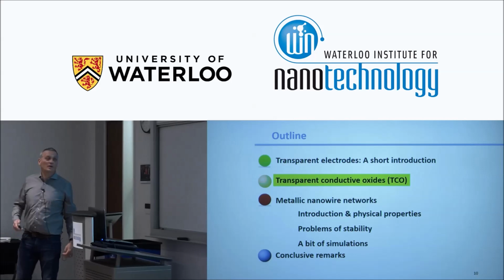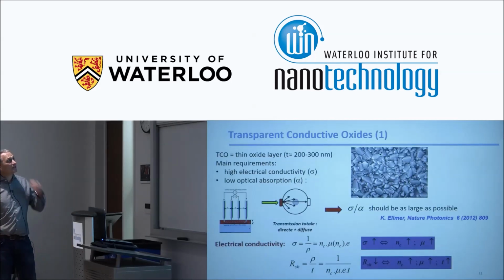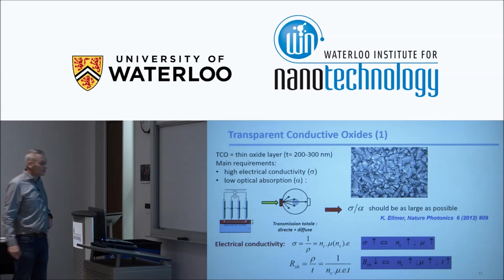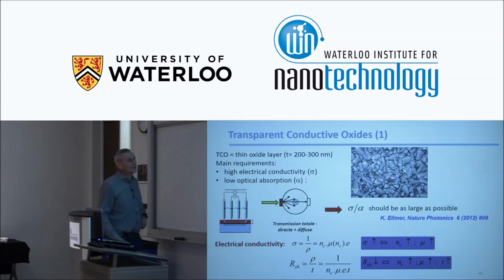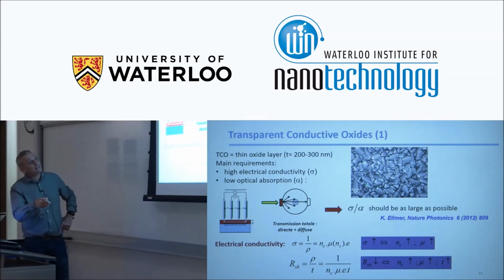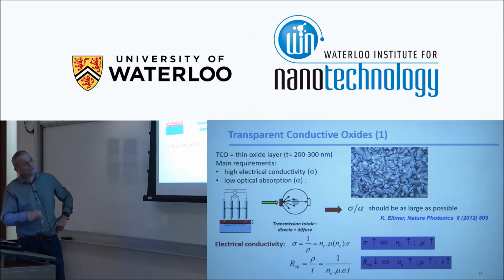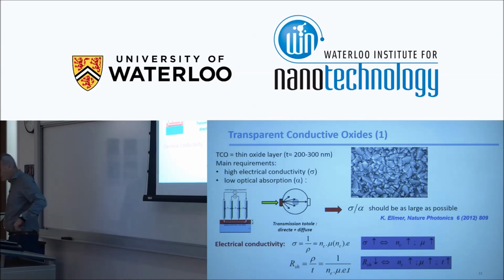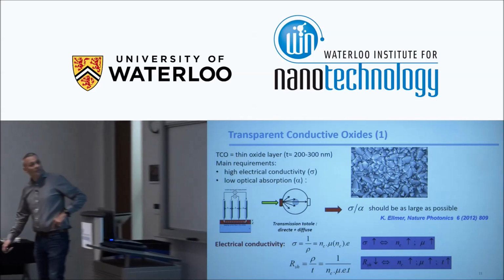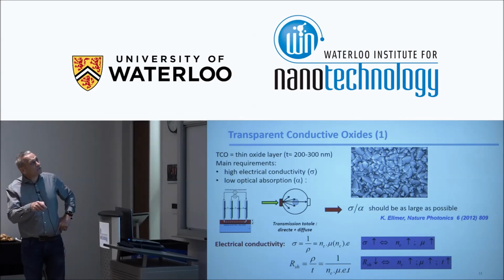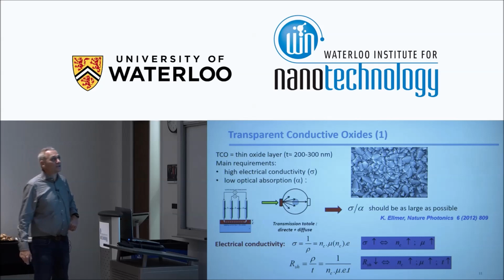Okay, so I'm going to talk a bit about transparent conductive oxides briefly, saying that they are thin oxide layers. The thickness is about 200, 300, 400 nanometers, and they look like this. This is the SEM picture. The scale bar is 200 nanometers, so you have a thin polycrystalline layer with a lot of grains. So the grain boundaries could play a key role. And for this FTO layer, you can also see there are some twins within grains, which can also scatter electrons.